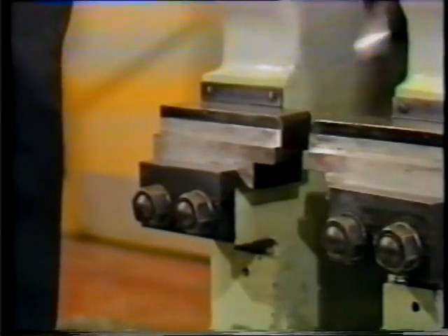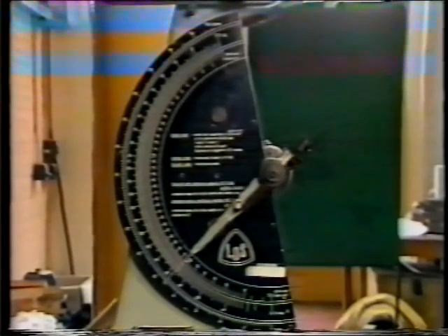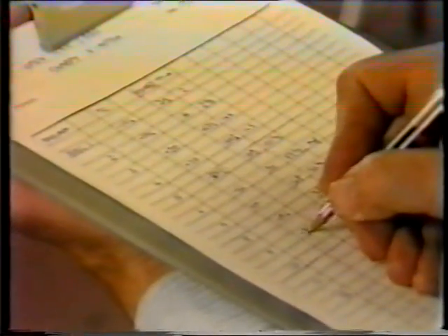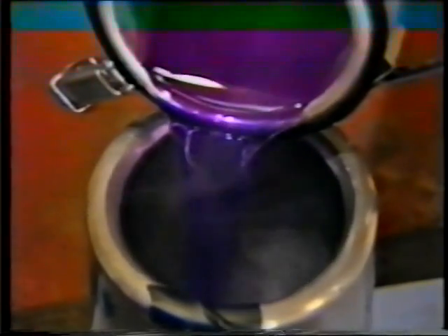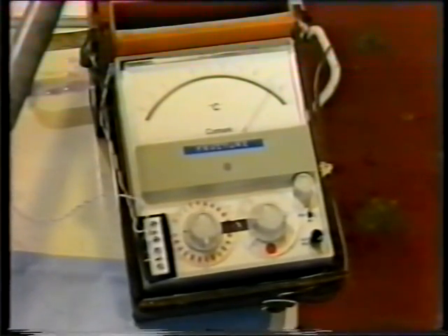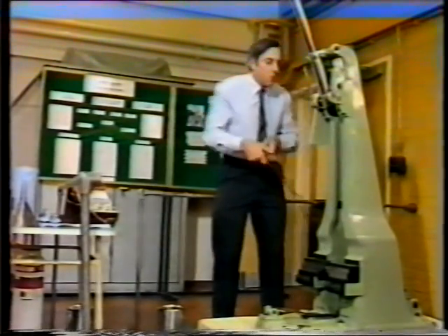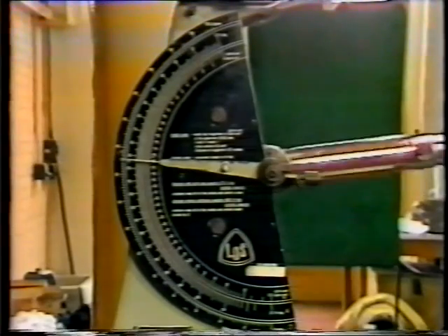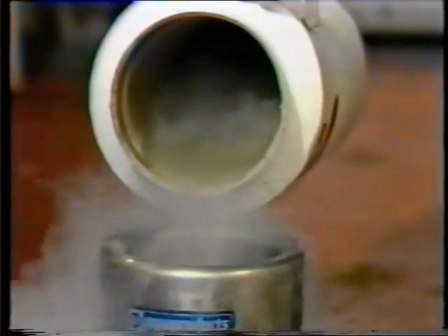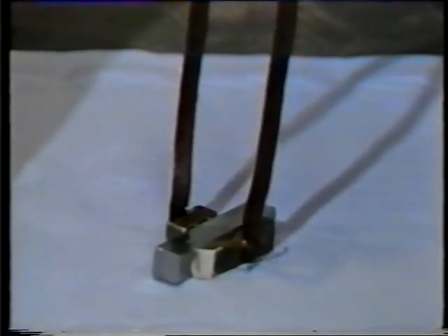What's being measured is the amount of energy absorbed by this specimen when hit by the swinging hammer. The smaller the angle through which the pointer moves, the tougher the steel. But that toughness is greatly affected by temperature. A cocktail of methylated spirit and liquid nitrogen, stirred but not shaken, is used to cool the specimen. A larger angle, so the steel isn't as tough as it was. An extreme test involves cooling the specimen to the temperature of liquid nitrogen itself, minus 196 degrees centigrade.